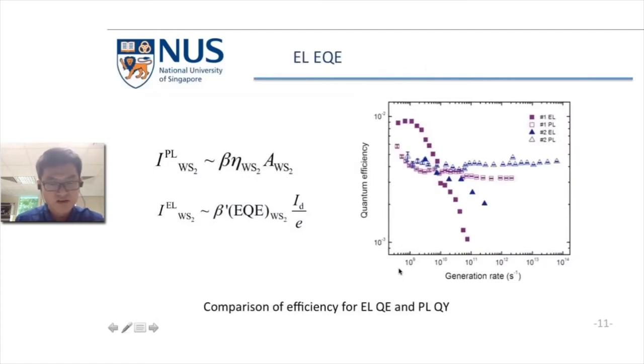To further investigate the quantum efficiency of the device, we compare the EL external quantum efficiency to the PL quantum yield. We can regard the EL process as two processes: first, converting the injected carrier to exciton; second, the exciton has the possibility to recombine and emit light. The second process heavily depends on the material quality and exciton radiative lifetime in the 2D semiconductor. We find the quantum efficiency for EL and PL are at a similar level, which means the carrier to exciton conversion efficiency is very high in our devices. The efficiency is only limited to the intrinsic quantum yield of the monolayer samples.